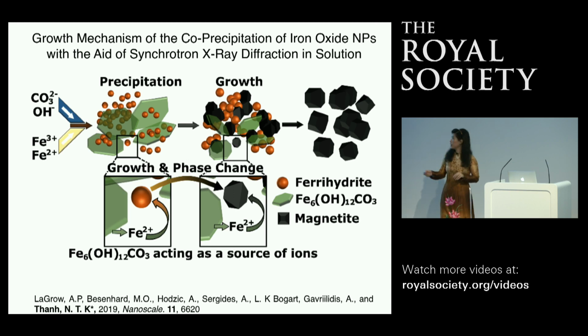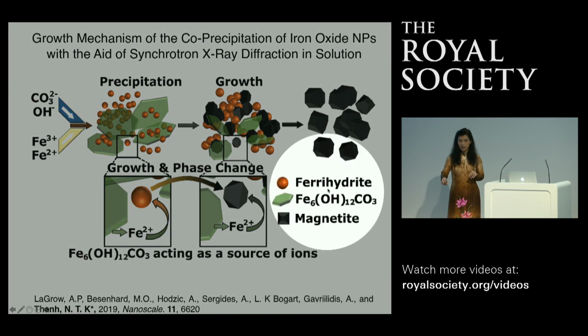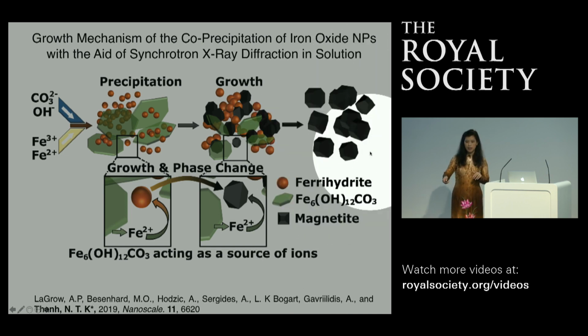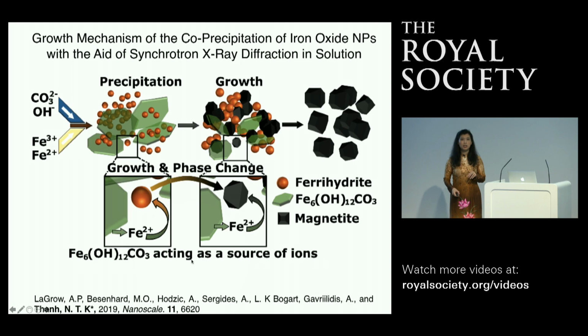What you want is the black magnetite, because it's very magnetic. You don't want any intermediate like the iron carbonate, the green plate in between. So you need to be able to control your reaction to minimize the intermediate, so that your reaction will be 100% if you can, forming only magnetite, not any other intermediate.